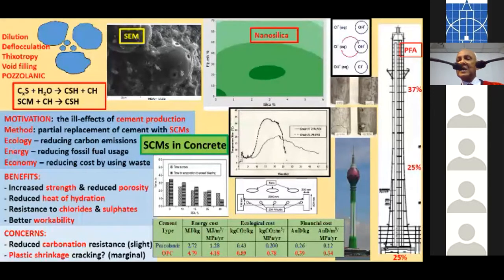Now for some of the new developments in PFA, before I go there, these are some samples from my Imperial College days. So I used fly ash there also. We were looking at the effect of, well, actually creep of concrete at high temperatures. But while we were doing that, we were heating concrete to various temperatures. Well, these were actually neat cement paste specimens. So this is a specimen heated to 375 degrees and then cooled back to room temperature. This is to 400 degrees C and cooled back to room temperature. There is a big difference between this and 25 degrees centigrade. Now this one is completely cracked.